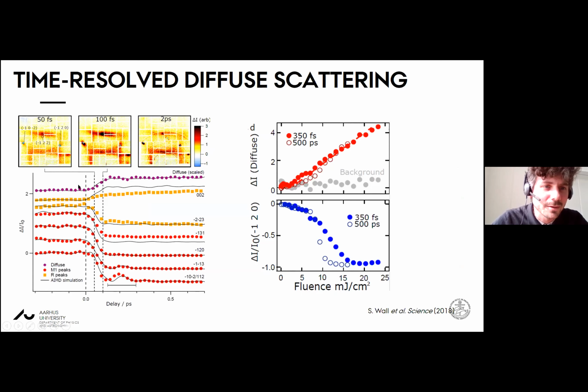So what are the timescales involved? Well, we can take frames from this movie and plot the diffuse scattering, which is a measure of the disorder in the system, the purple dots here, compared to the Bragg peaks. VO2 is a little bit more complicated than the simple picture, so all the peaks labeled red should go to 0 when they're photoexcited, and they nearly all do. The peaks labeled yellow are present in the rutile phase, so in principle they should go up, but because of the structure, some of them actually go down as well. The lines are results of molecular dynamics simulations for the phase transition, which have no free parameters. The exception is the solid line for the diffuse scattering, which is literally Q squared rather than the total diffuse scattering, but they're very similar to each other.